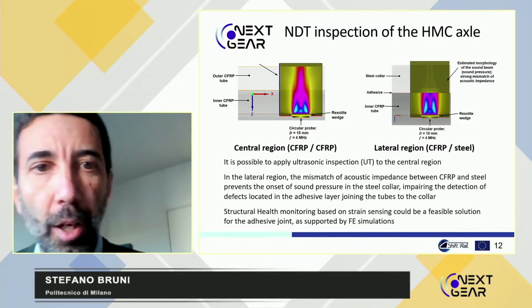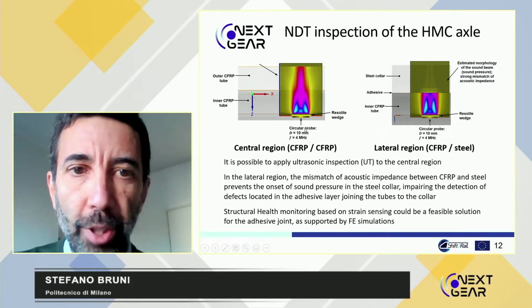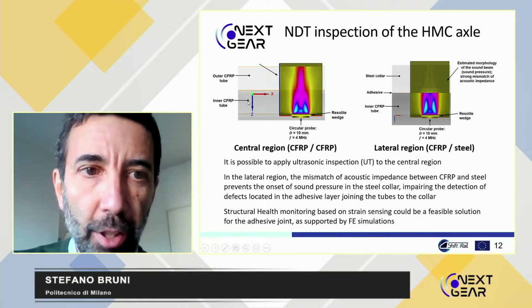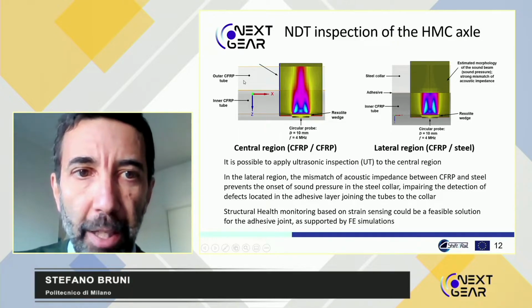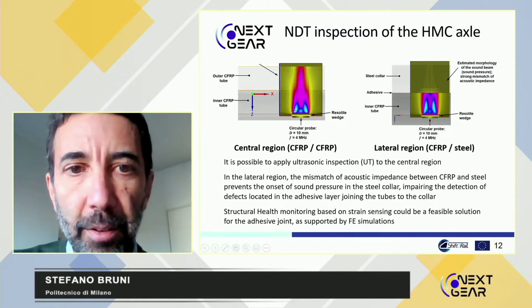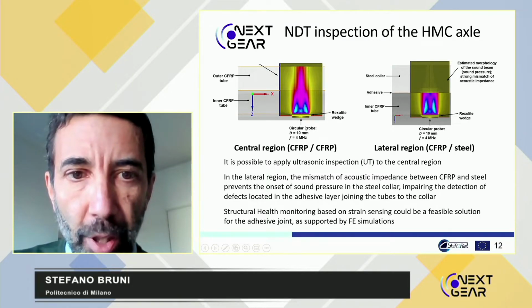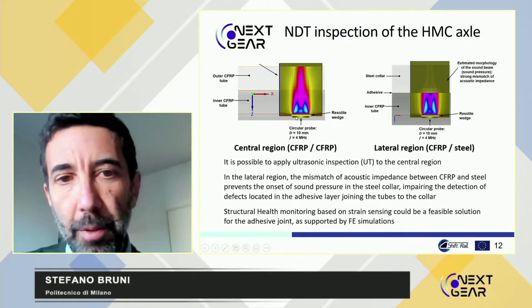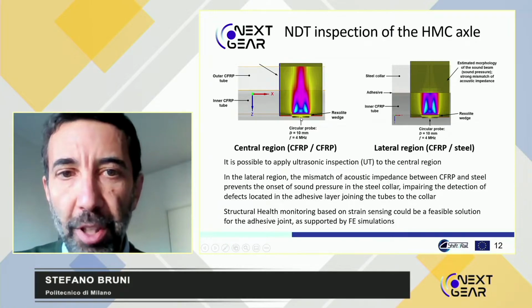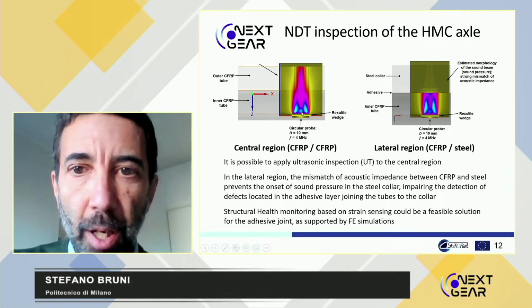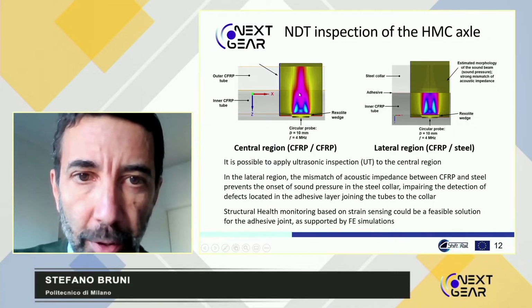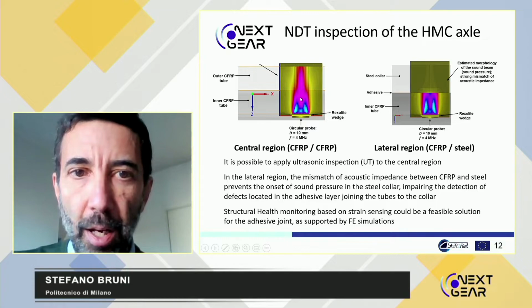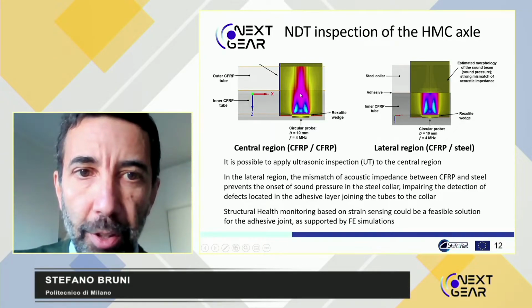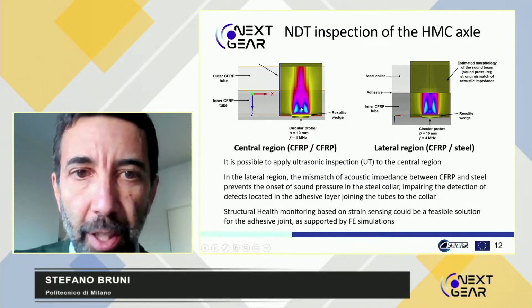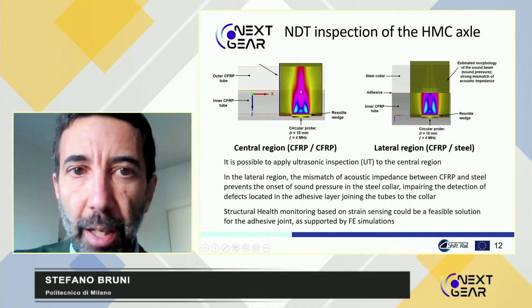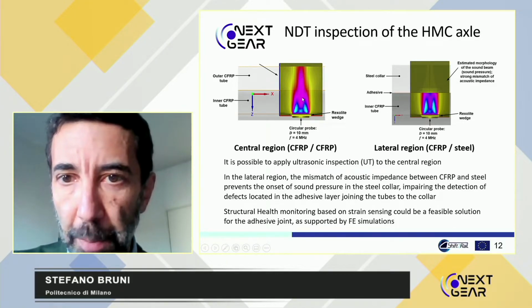the axle. We found that as long as we look into the central part of the axle, where we have the joining of the inner and outer tubes, which are both made of the same material, the composite material, then, as you see from this image, you see here the circular probe used for the ultrasound inspection. And this map shows how the ultrasound waves propagate into the material. And you see we have a nice transfer of the ultrasound waves from the inner tube to the outer tube, which means basically the entire thickness of the axle can be properly inspected, effectively inspected.